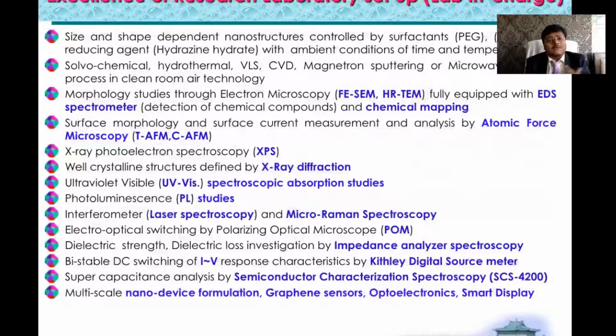So first, what I did, we synthesize our basic bulk material. We started with salt, and our motivation is size and shape dependent morphology. So that's why we use some surfactant. Let's say polyethylene glycol or CTAB is a surfactant. Sometimes we use hydrazine hydrate, which is a capping agent that should accelerate our chemical reaction.